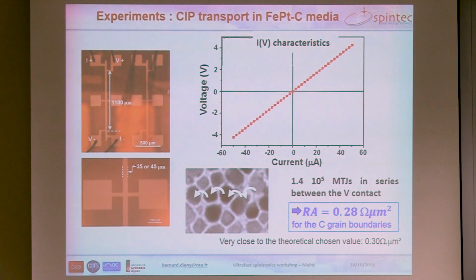And so the sample, this media, has been patterned in the form of a stripe like this, with 4-point contacts. And we applied a current between the two external contacts and measured the voltage across the device. So we inject current through the external contact and measure the voltage between the inner contacts. And we got this IV characteristics, so very linear.